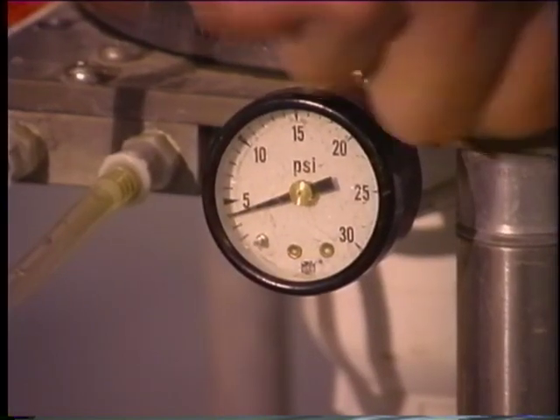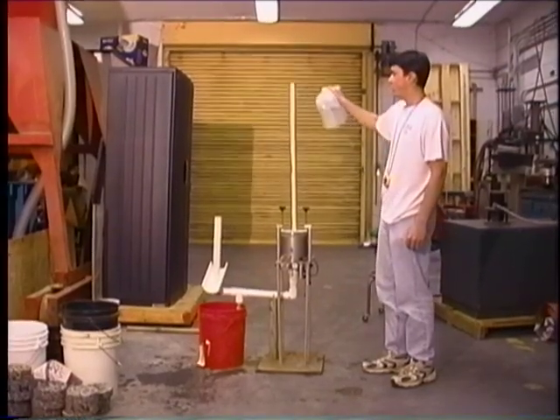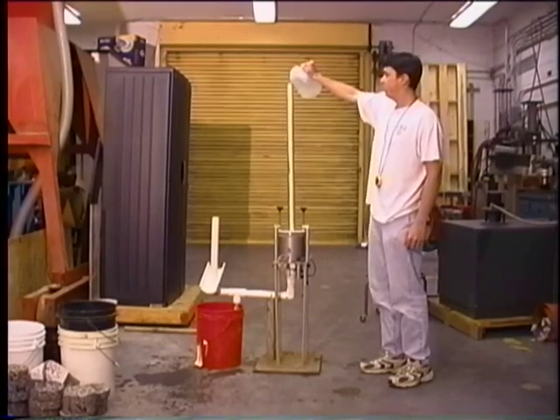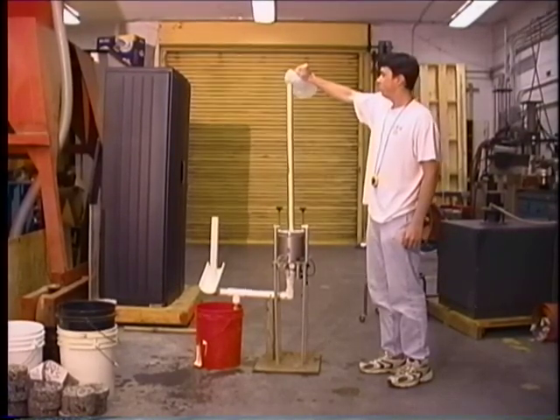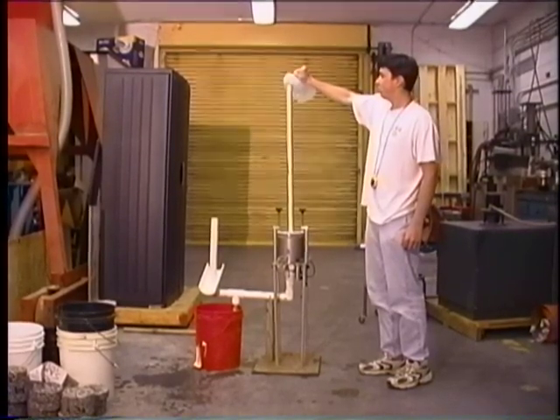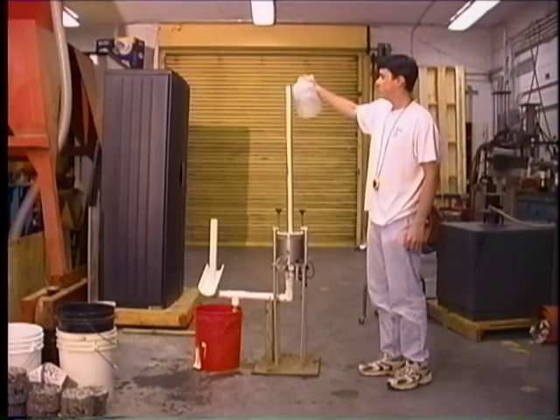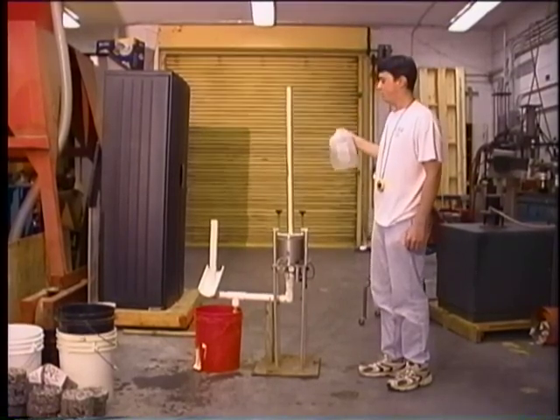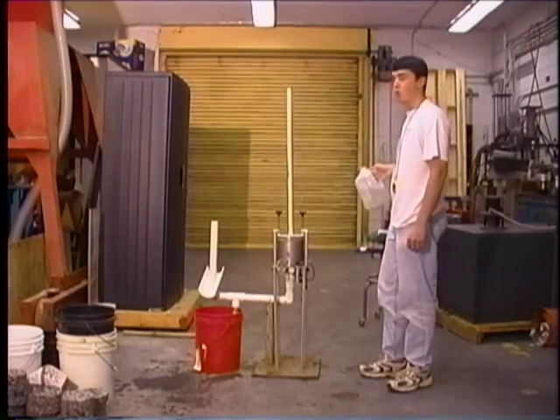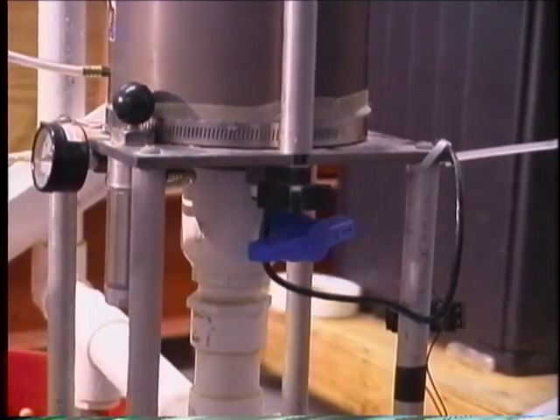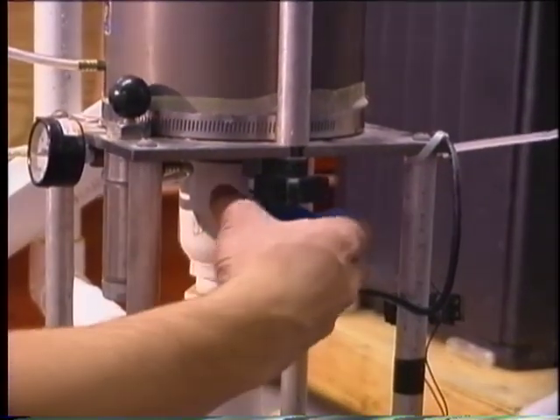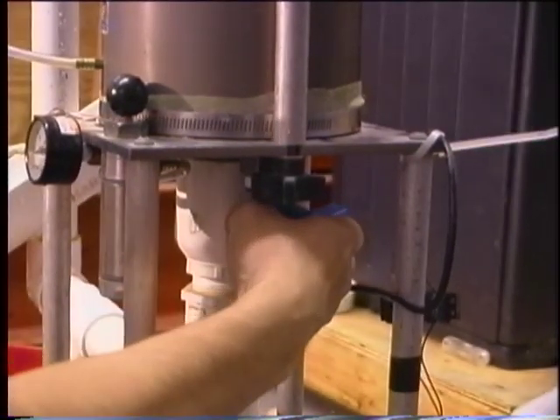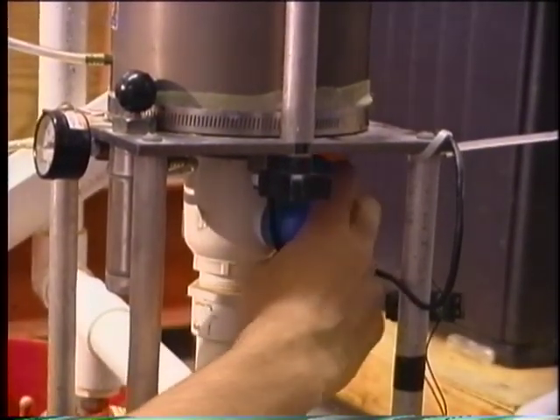Once the system is pressurized to at least 5 pounds PSI, fill both tubes completely with water. The pressure line must remain on the pressure nozzle to maintain constant pressure. At this point, you are ready to begin testing. Opening the upstream or blue valve under the stand starts the test. As the valve is opened, start a timer.